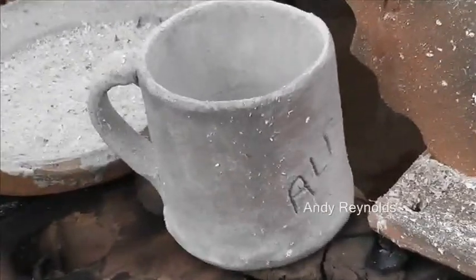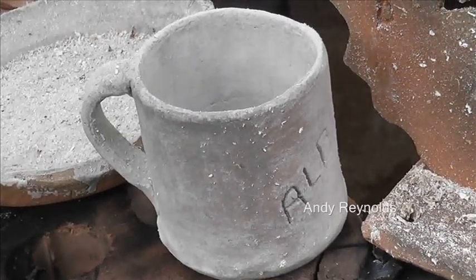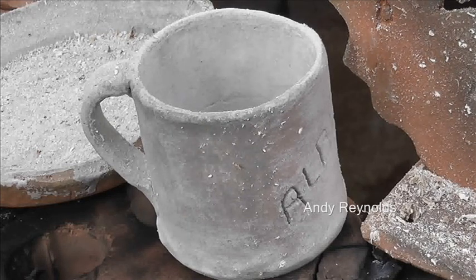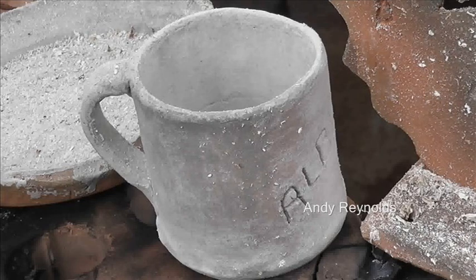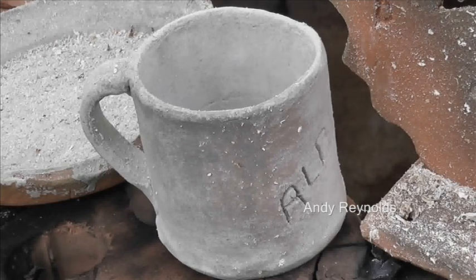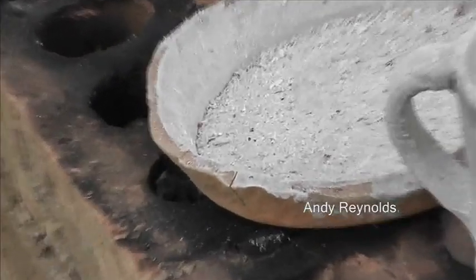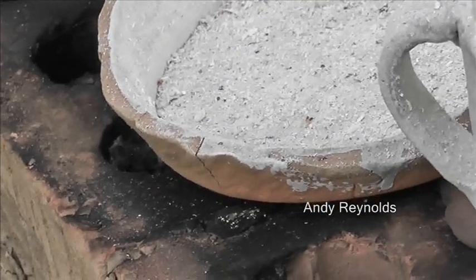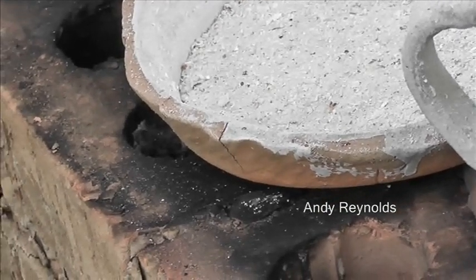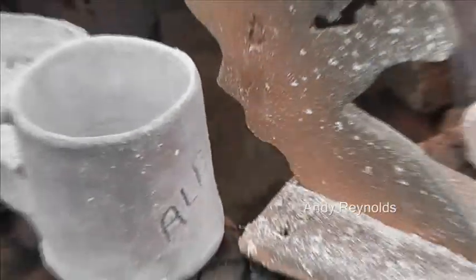These ones - that was supposed to be Mako low fire matte transparent, and it isn't. We got up to 960 - was that not enough? It doesn't look like it's melted. And this other dish - this is the one that was cracked across the base but not up the sides, and now there's a crack up the side. It's supposed to be a thousand degrees or 990. Does 960 to 993 make a difference? Well, it looks like it does. More things to learn.